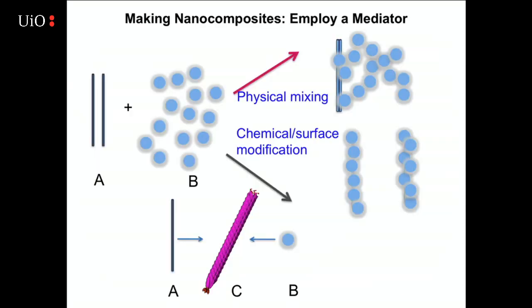But one of the things that we like about the M13 bacteriophage best is that it is this squishy structure, so you can think about actually having it do multiple things at one time. You can think about it having grow or bind a nanowire, and then simultaneously grow a nanoparticle. And so if you have, say, carbon nanotubes in this case and titanium nanoparticles, you can think about mixing them at the nanoscale.